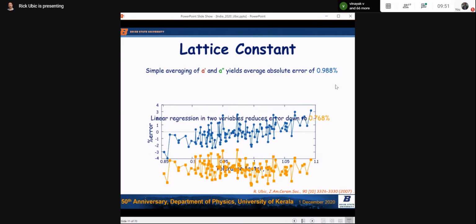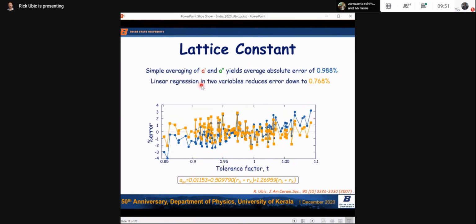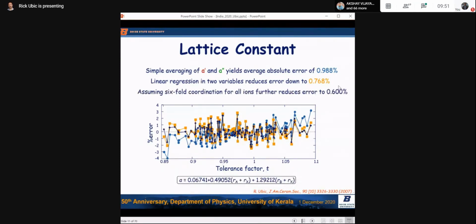But what if, instead of taking a simple average, we do a linear regression in 2 variables? That's the orange data points. If we do that, we get a slightly better result, 0.768% average absolute relative error. And then we do something a bit weird. We put everything in 6-fold coordination. We use 6-fold coordinated radius data, anyway, from the Shannon tables, and we get the best result of all, 0.6%. You have dark blue data points on here, hovering around the 0 error line. And there's the equation for that. So that's the best result we achieved for ABX3 perovskites.